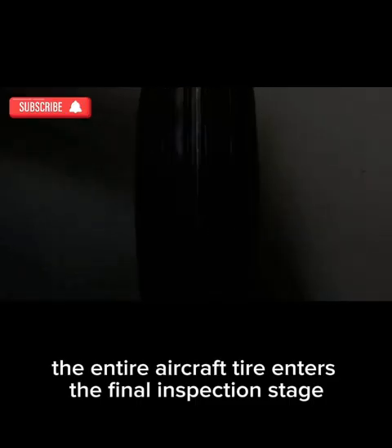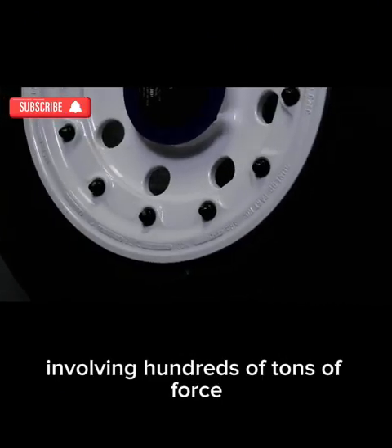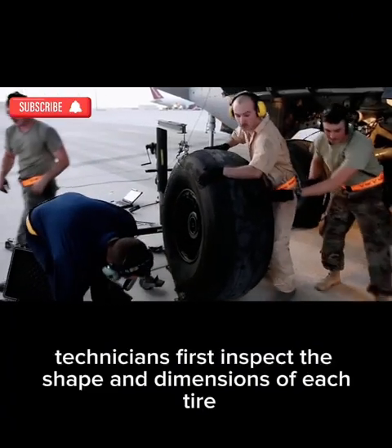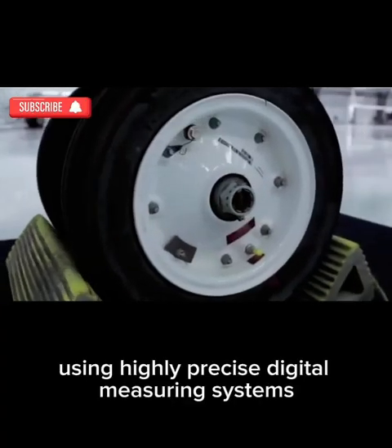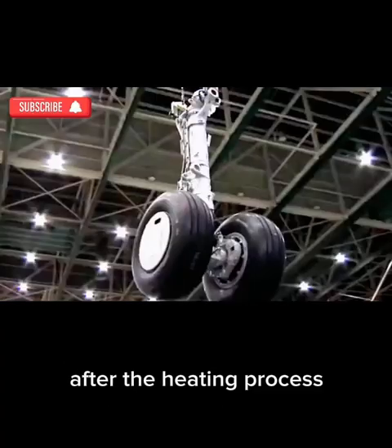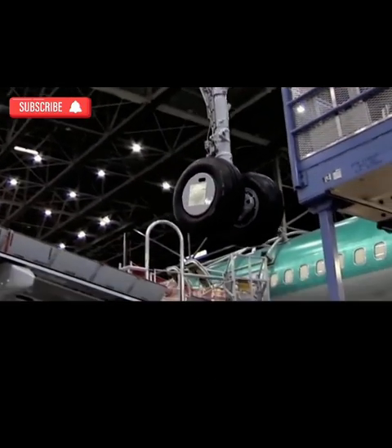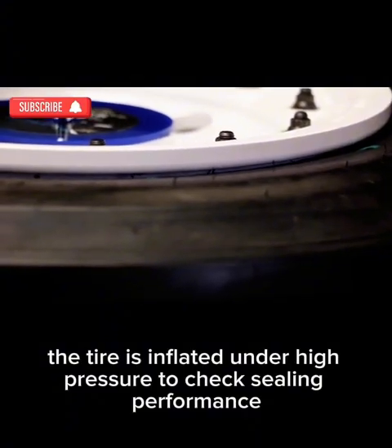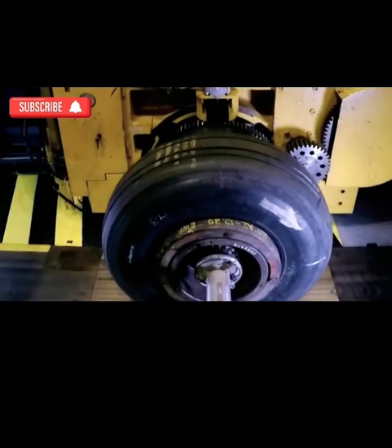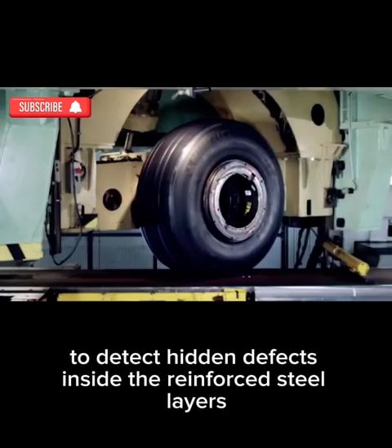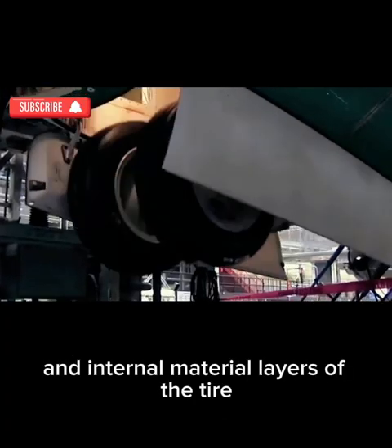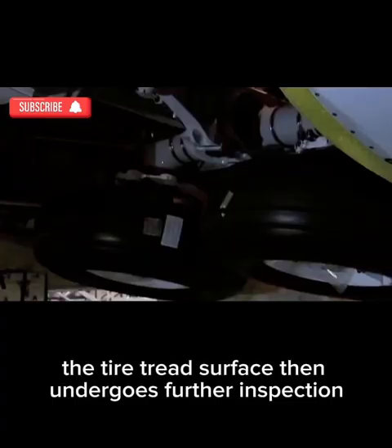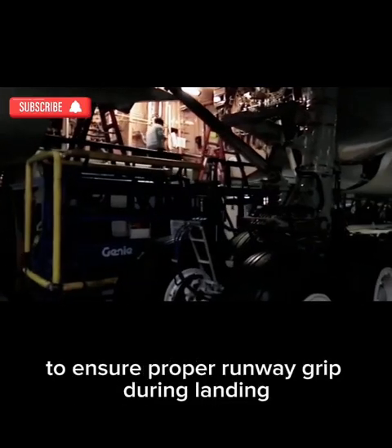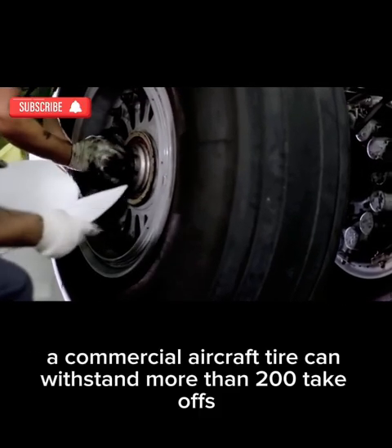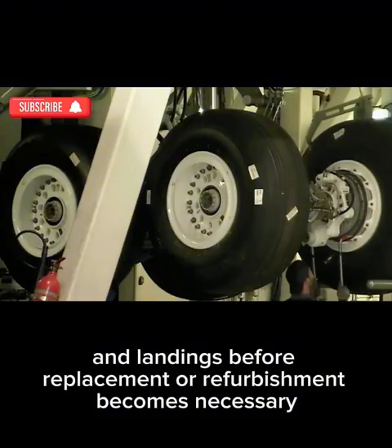After vulcanization is completed, the entire aircraft tire enters the final inspection stage, the process that determines whether it can withstand landings involving hundreds of tons of force. Technicians first inspect the shape and dimensions of each tire using highly precise digital measuring systems to ensure that the overall structure remains stable after the heating process. Next, the tire is inflated under high pressure to check sealing performance and load retention inside the rubber structure. Some factories also use industrial X-ray systems to detect hidden defects inside the reinforced steel layers and internal material layers of the tire. The tire tread surface then undergoes further inspection to ensure proper runway grip during landing. On average, a commercial aircraft tire can withstand more than 200 takeoffs and landings before replacement or refurbishment becomes necessary.